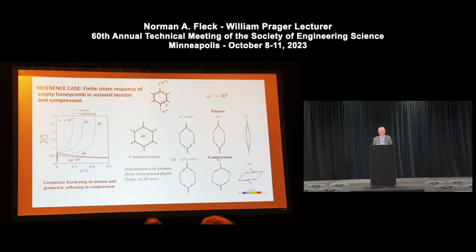For the empty case, I'm showing here the compressive response. And in all cases, for all values of that inclination omega, one gets a softening behavior, loss of volume, bending type response here in compression. Here's the bending type response. And this is our familiar friend in the sense of how crush bands will form in an empty honeycomb.